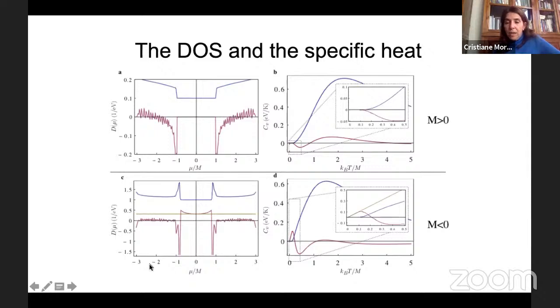But now I can calculate the density of states in the topological phase for m equal -1, for instance. And again, now the blue curve has been shifted up from 0. This would be 0. So in this regime, the bulk is gapped, it has 0 density of states. But look now at the edge, the edge has a finite density of states. And this is precisely the topological phase between -1 and 1.